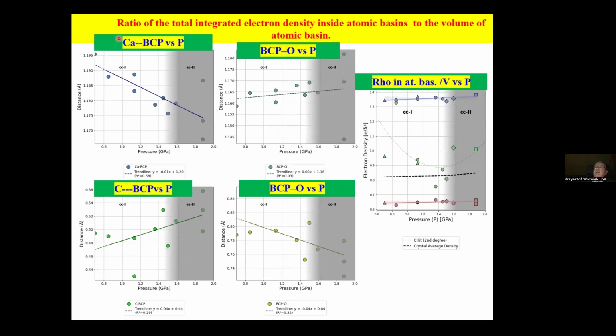We can also see how this critical point, this weakest point of a bond, is shifting with pressure. For example, in this case, the distance to calcium ion is decreasing, means this critical point is going closer to calcium and is slightly escaping from oxygen atom. And in the case of carbon atom, we see big scatter.